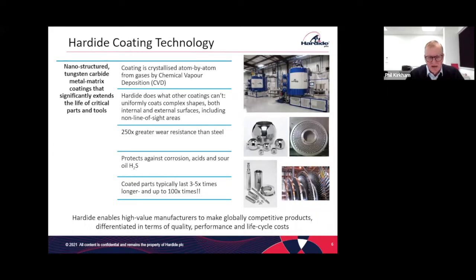So it has a very high wear resistance, something like 250 times greater than uncoated steel. Because of the way the coating grows atom by atom, they all link together. There are no voids or porosity in the coating, so nothing can get through the coating to the substrate. So it's a very good barrier for corrosion and acids. And in the oil industry, which is significant to us, particularly there's H2S, hydrogen sulfide in the oil, which is a very aggressive media. And typically, the reports we've had from the markets are parts last 3 to 5 times longer than normal, and we have had reports of lasting up to 100 times longer than normal.